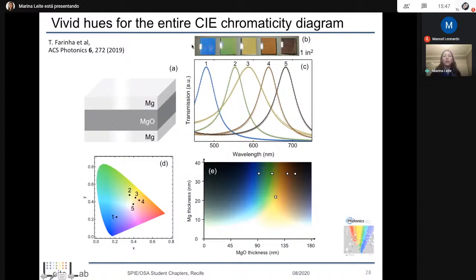So that's what you see here in B, in this top row: real color photographs of 2.5 centimeters by 2.5 centimeters pieces of glass, in this case as the substrate, with the MIM structure on top. By the way, I'm mentioning glass, but there are biocompatible polymers that worked very well with the system as well, which we are working on right now. But anyway, as we increase the MgO layer's thickness, we can redshift the peak transmission.